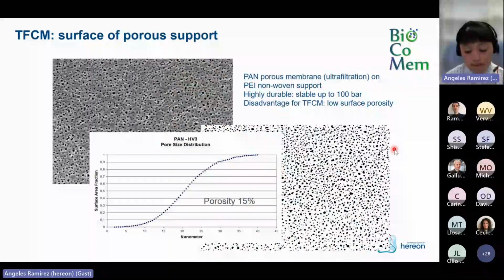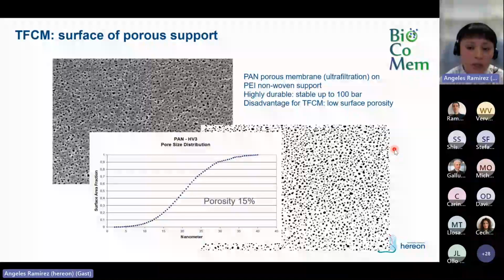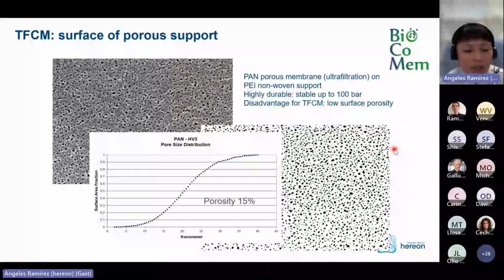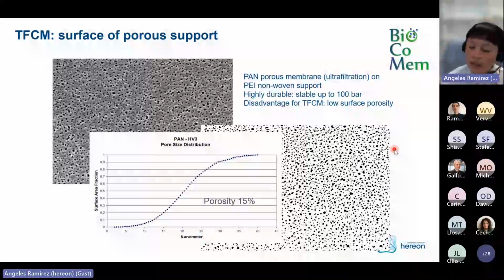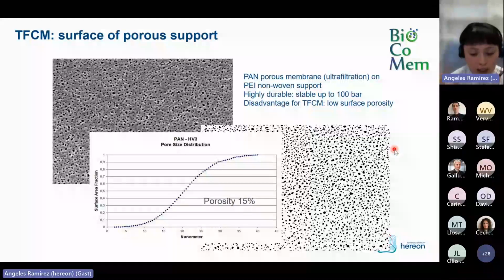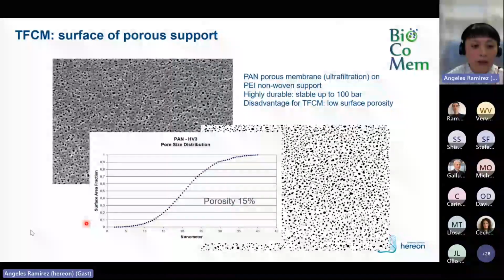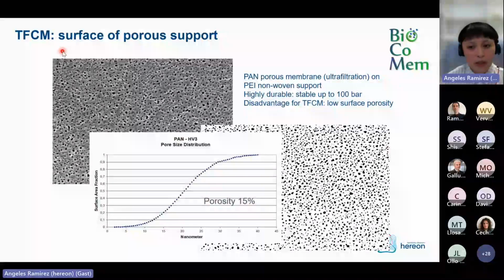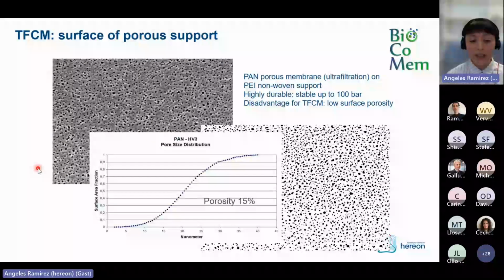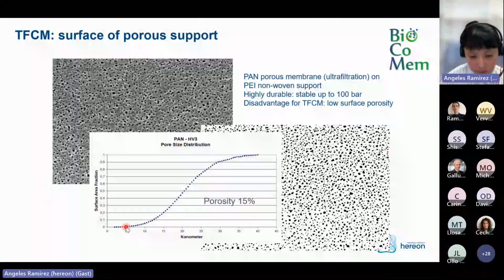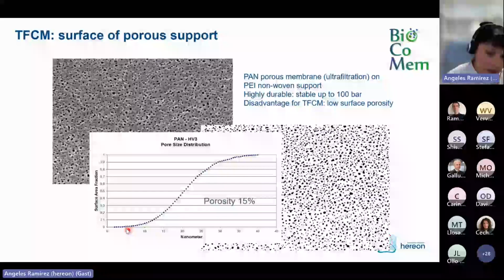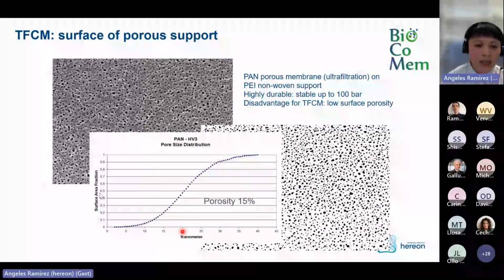Now, the porous support is one of the most important parts of a thin film composite membrane, as I mentioned before, because it allows these thin layers to be used at pressures up to 100 bar, for example. And the most important feature of this type of ultrafiltration membrane is the surface porosity. Here we have the example of a polyacrylonitrile porous membrane, which is a very robust polymer. And we can see here that the pore sizes range roughly from 5 to 40 nanometers, with an average pore size of 20 nanometers.